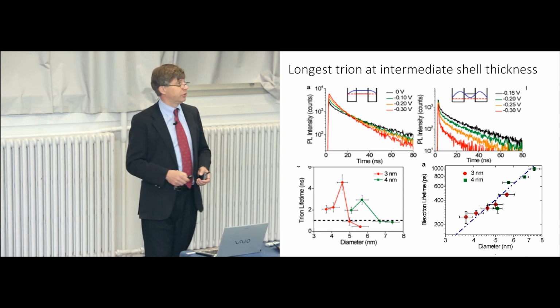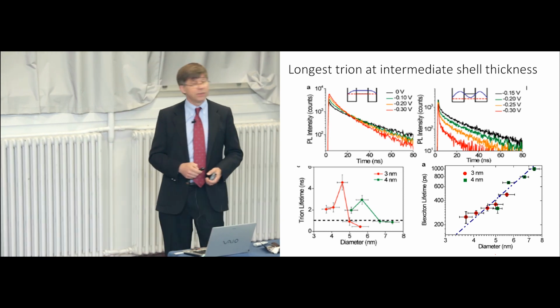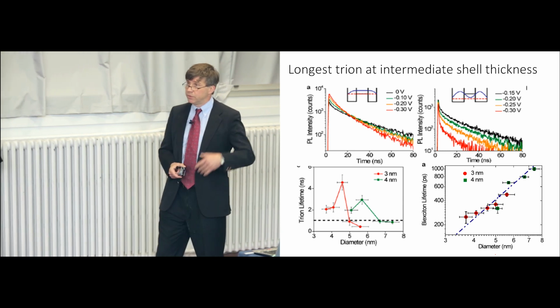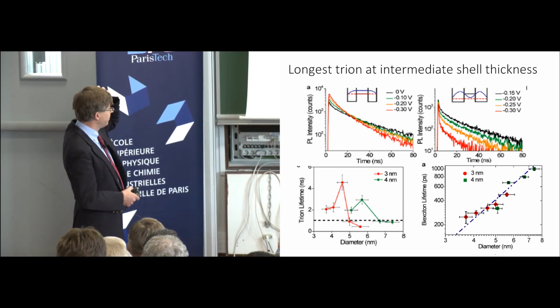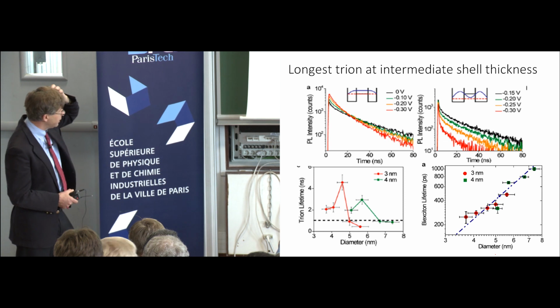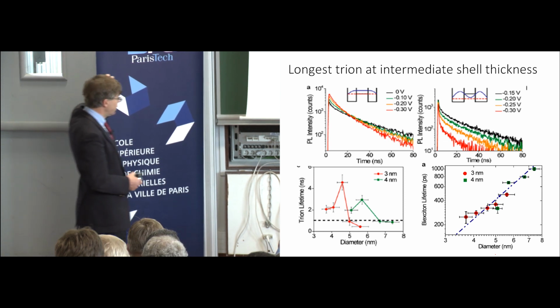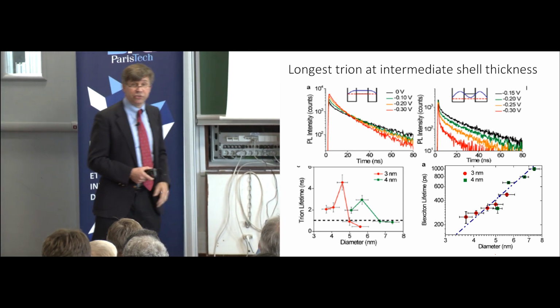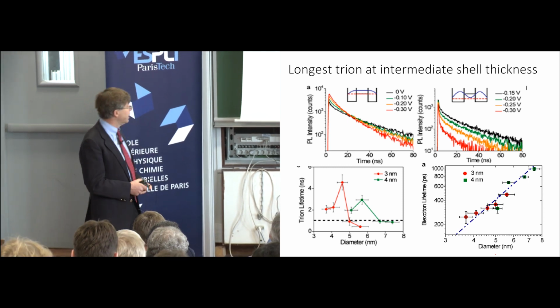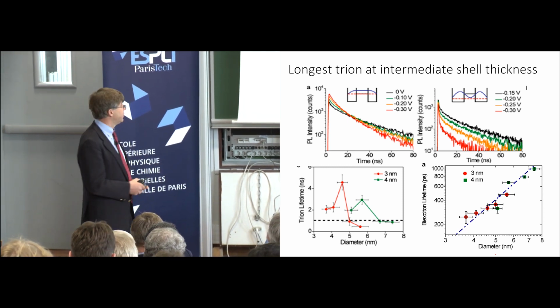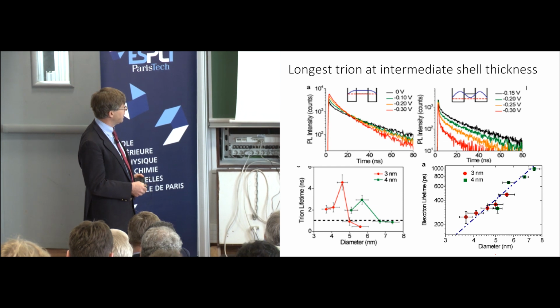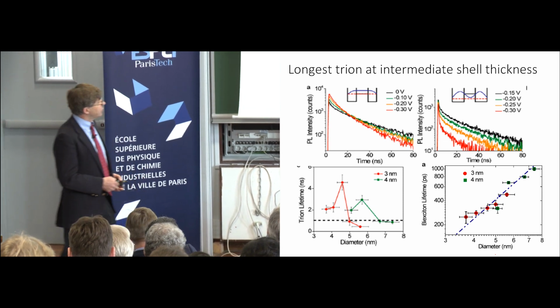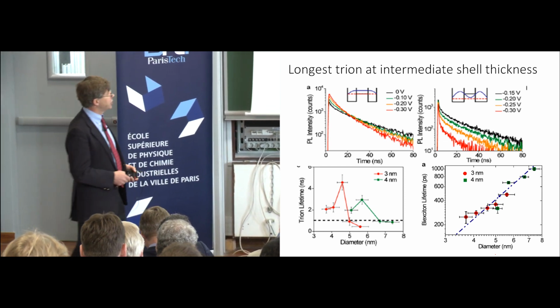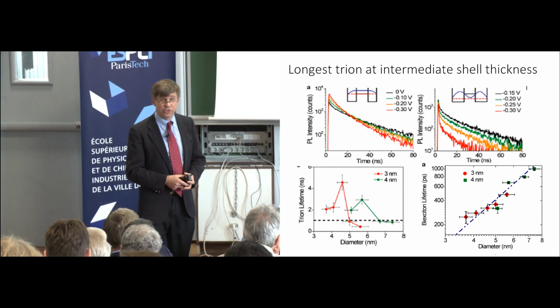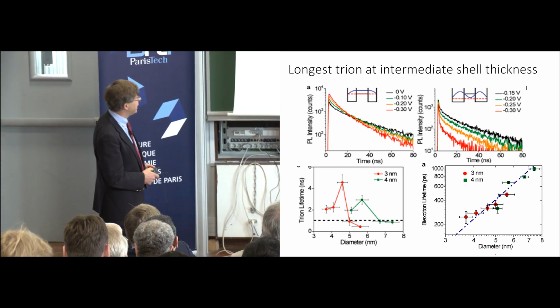So it's very strange. So the first time Wei Qin saw this result, I told him, well, maybe it's a problem of growth, and you get some defects after some thickness of shell, and things are going wrong. So he tried a different synthetic approach for the shell, did, of course, his TEM work, and then tried a different core to see if this would happen differently, and he found more or less the same thing with a different core. So that was fine, and then we said, well, we better check the biexciton lifetime. It should show the same effects, this kind of non-monotonous behavior.